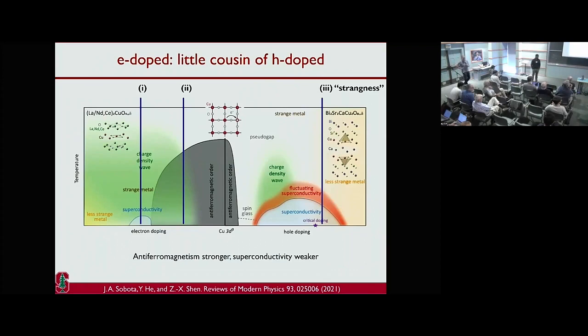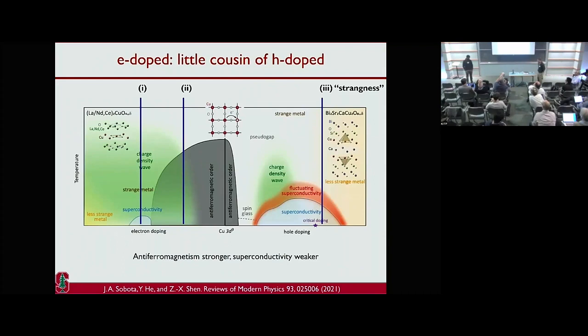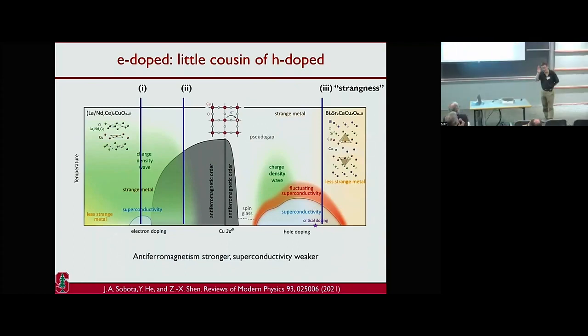So with respect to doping 0.15, did I understand you correctly that you wouldn't expect quantum oscillations there from what you see? I would say if the quantum oscillation will be seen in a similar doping region, it's a subtle thing. We knew that even at nominally 15% doping, if you anneal the sample differently, you would have somewhat different results. In other words, the nominal doping is one of the parameters of that. There could be a percent of difference.